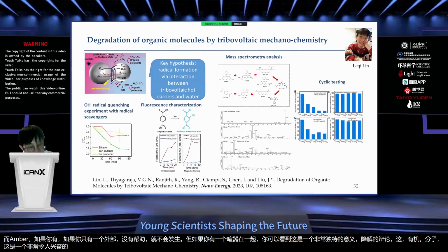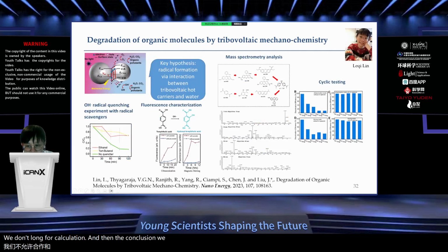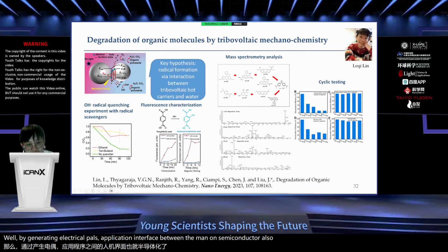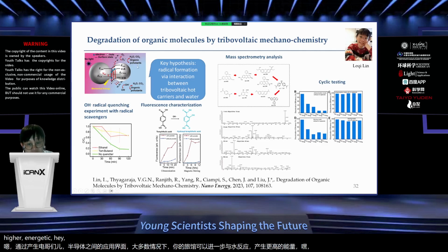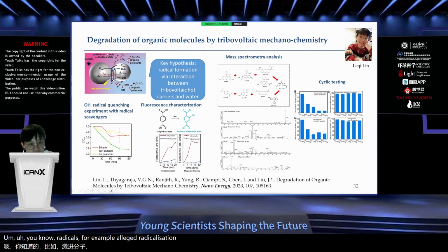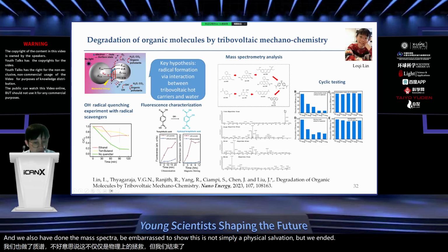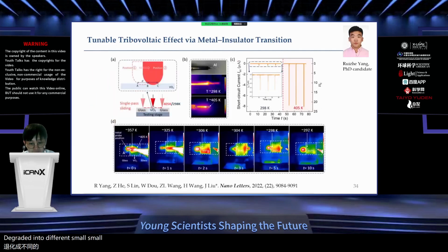We've done a lot of characterization, and the conclusion we have is that by generating electron-hole pairs at the collision interface between the metal and semiconductor, those electron-hole pairs can further react with water to generate highly energetic or highly oxidative radicals, for example, OH radicals and O2 radicals. Those radicals can be demonstrated from fluorescence spectroscopy. And we have also done mass spectroscopy analysis to show this is not simply physical absorption, but we indeed degrade it into different small molecules.